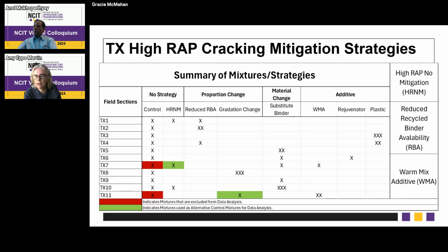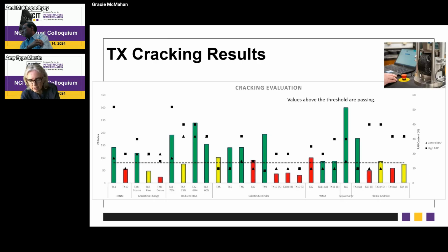So we looked at a bunch of different strategies: proportion changes, material changes, additives, and we compared all of them back to a control. And the control is usually a typical RAP content, like 20% or below. And we compared their cracking resistance and their rutting resistance. So this just gives you a snapshot of the different sections that we looked at, some of them in the lab, some of them in the field, and which different strategies we're able to look at. Next slide, please.